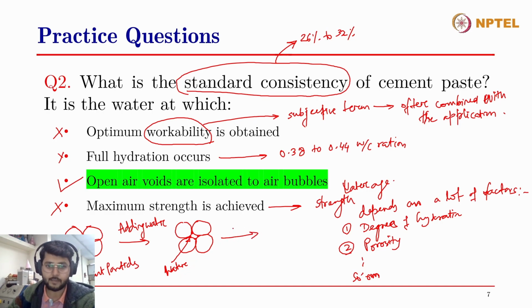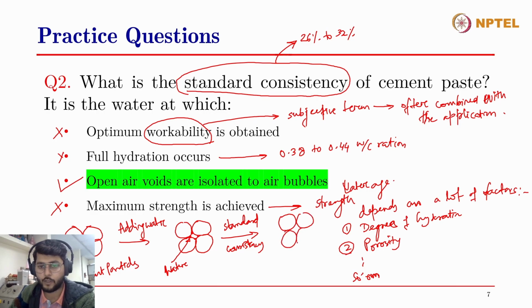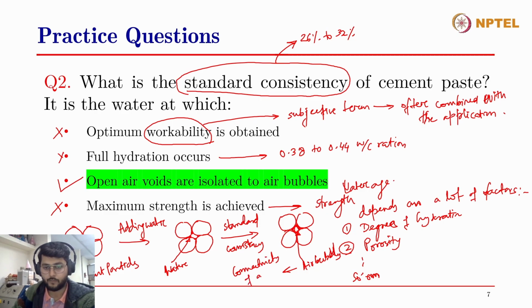But when the cement is at its standard consistency, what happens is the connectivity of the air voids is lost. So the water takes most of the void volume, and the air voids are reduced to air bubbles. So the connectivity of air voids is lost.